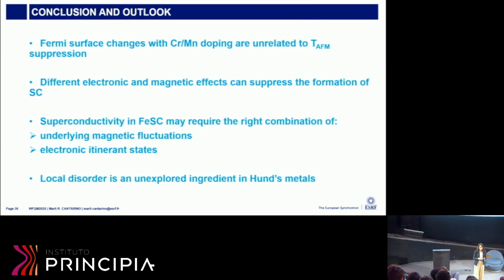So now that I've talked too fast and too much, the conclusion and outlook is that the Fermi surface changes with chromium and manganese are different, and they are unrelated to the transition temperature.